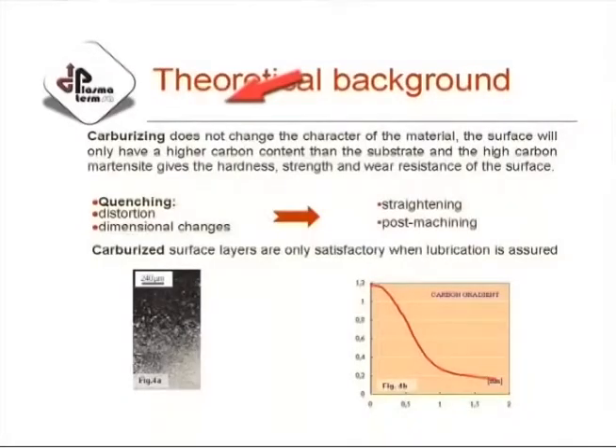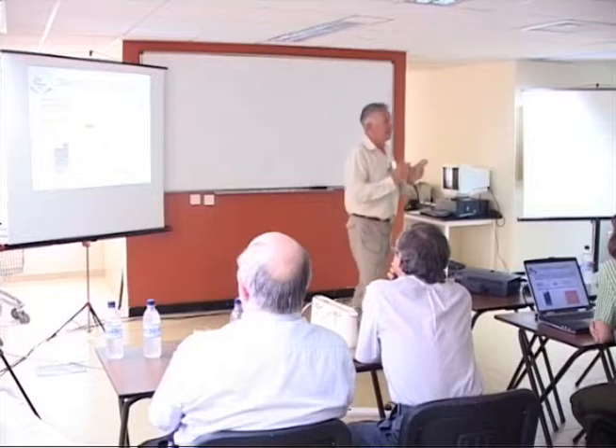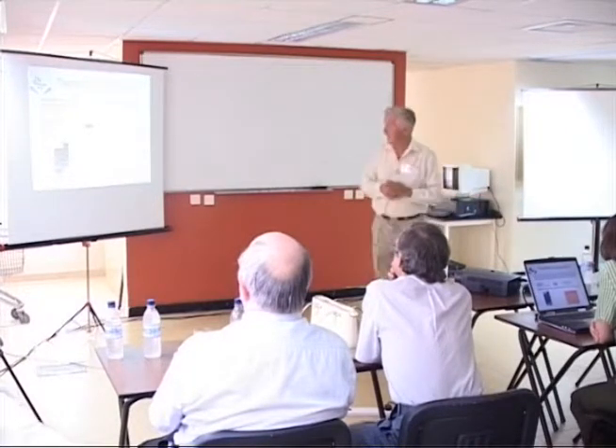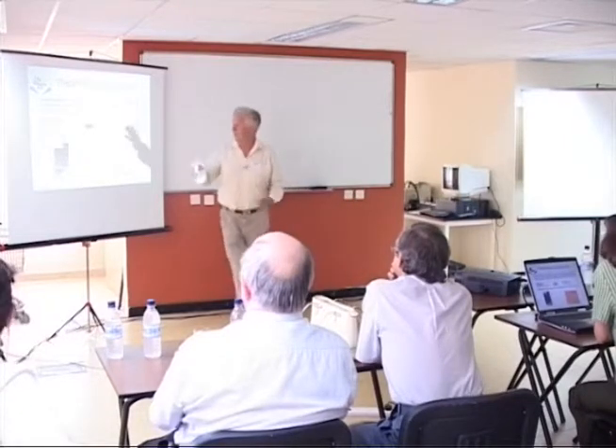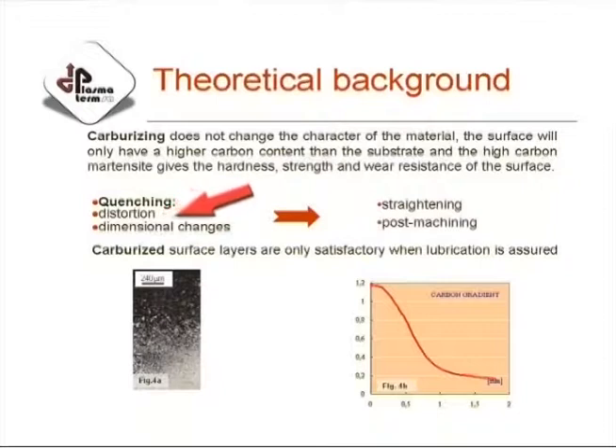Well, carburizing does not change the character of the material. We just introduce carbon in the surface, which will give a higher carbon martensite in the surface, and certainly this will lead to a typical carbon gradient in the surface, and this typical carbon gradient will be reflected also in the hardness plot, hardness against the depth. It's well known for all of us. So that's typical for carburizing. The problem, just as I said, is the distortion, quenching, the dimensional changes, which mean you need straightening and you need post-machining. And you have seen the typical damage of the surface in process.